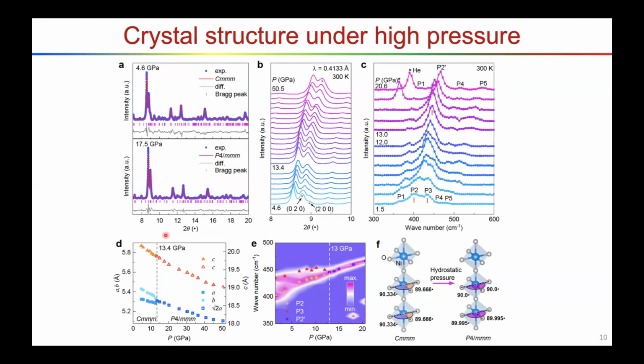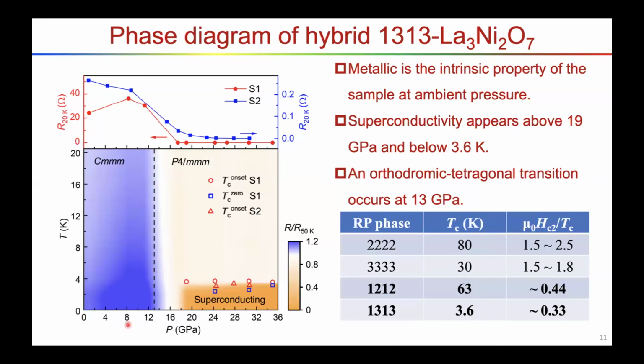We need to notice the structure transition appears at 13 gigapascals, but the superconductivity appears around 20 gigapascals. That means the structure transition is separated from the emergence of superconductivity. Okay, so here's the phase diagram.